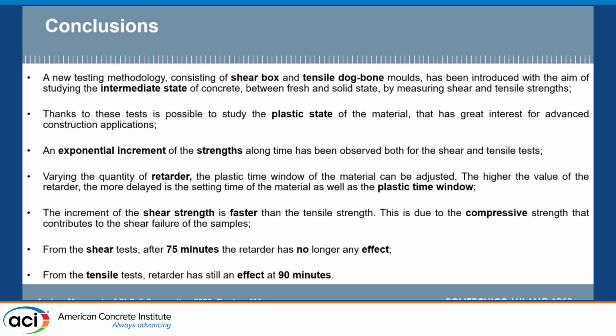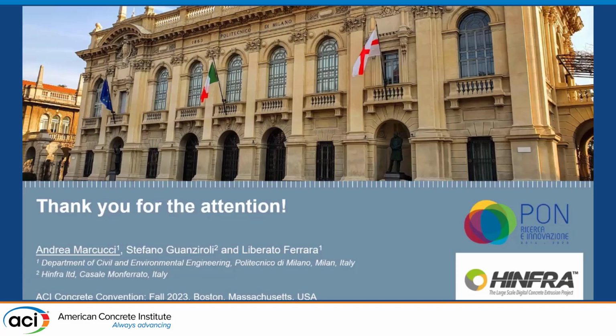And the increment of the shear strength is faster than the tensile strength. And this may be due to the faster development of the compression stress that influences the shear strength of the material. For shear test, after 75 minutes, the retarder no longer has any effect, whereas at tensile test, the retarder has still effect at 90 minutes. So, thank you for the attention.